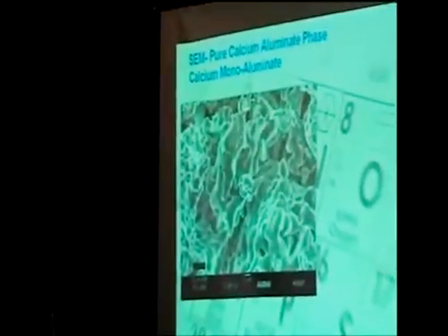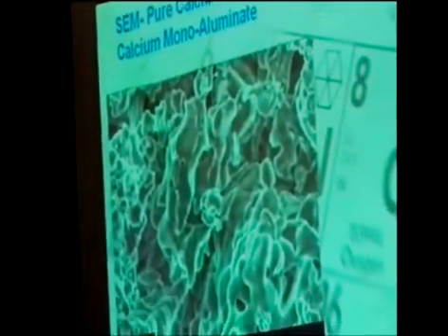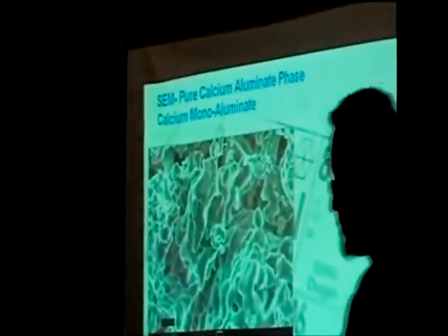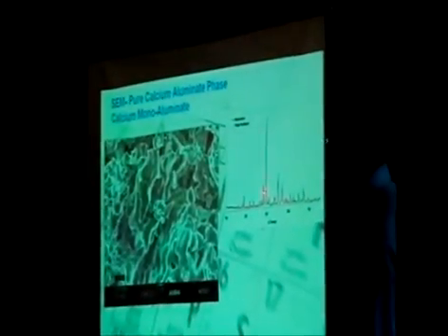This is the SEM picture for this calcium aluminate, one calcium, one aluminum. You can see here these small particles milled, and there's some sugar here, and they bind it together in order to get some kind of strength, but it's still porous. And this XRD again, quite pure phase, fit nicely. Some unidentified peaks, but the majority fit pretty well. And we did some study here.